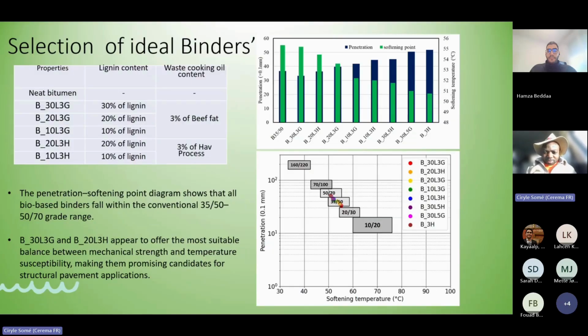And here I show you some results. It's not all the results. I selected the good ones. We tested several combinations. For example, when I write here B30L3G, it means bitumen with 30% of lignin and 3% of fat. On the right side of the slide, you can see the evolution: the blue one is the needle penetration test performed at 25 degrees, and the green one represents the softening temperature.